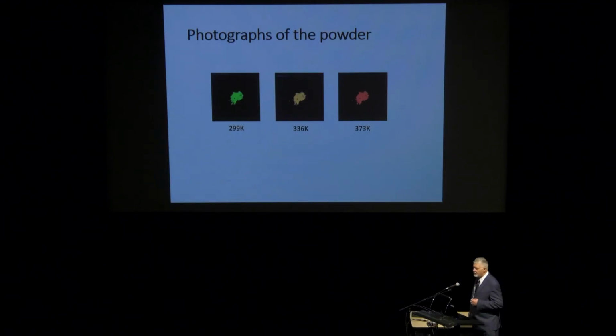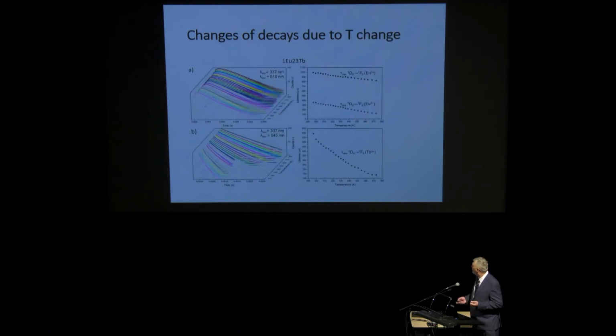This is just powder. We can process it in any way we want. We could make it nano size, we could make it micron size, but that's just powder. And as you can see here, the changes of color are really very, very well visible. And also we can follow the lifetime, which is another indicator of the temperature, which is independent. So we can have ratiometric measurement of temperature, or we can do lifetime measurement of temperature.